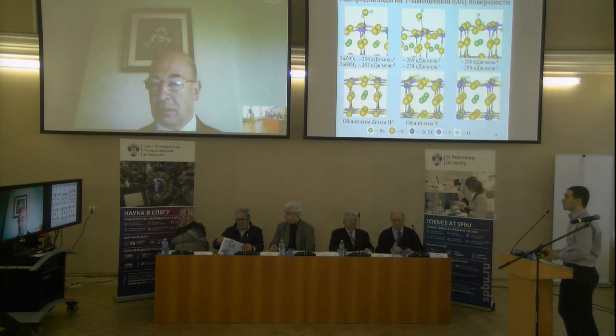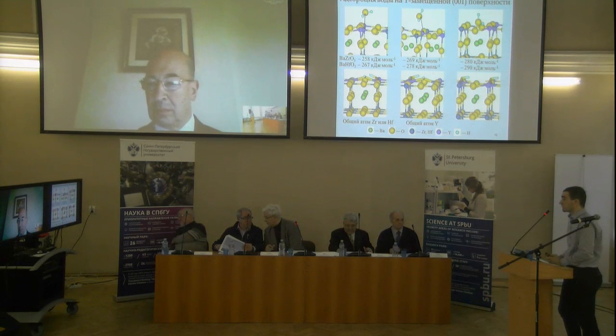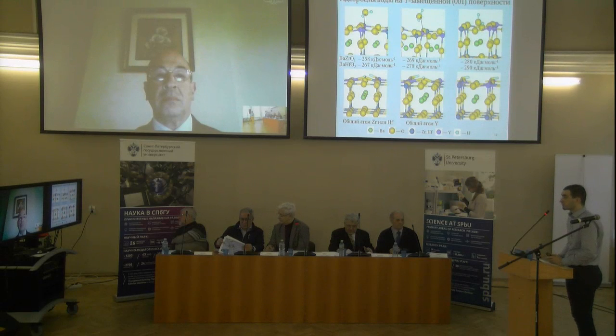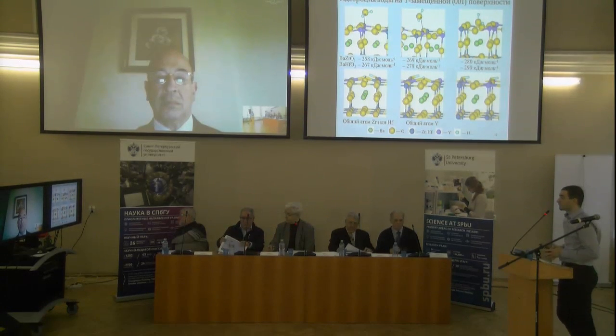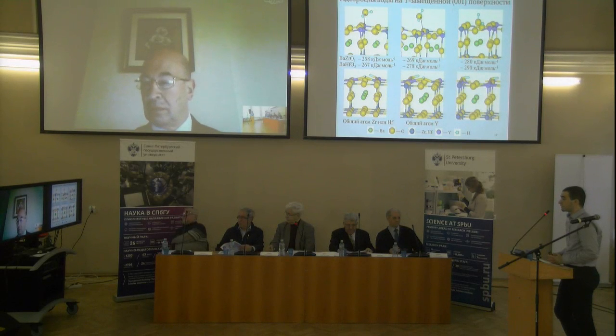Calculations of water adsorption on BaHfO3 and BaZrO3 surfaces were carried out using both primitive and doubled extended elementary cells. This means that there are two electropositive adsorption centers in the unit cell, and consequently two surface coverages can be considered depending on whether the water molecules occupy a single adsorption center, a semi-monolayer, or both, a monolayer.